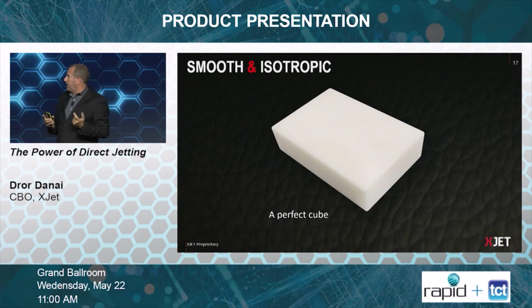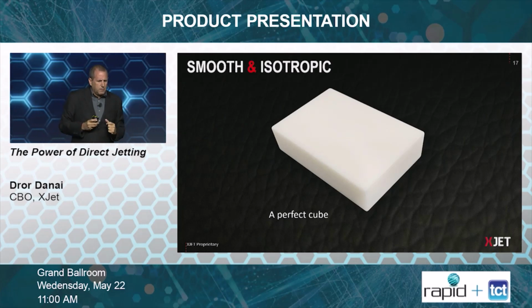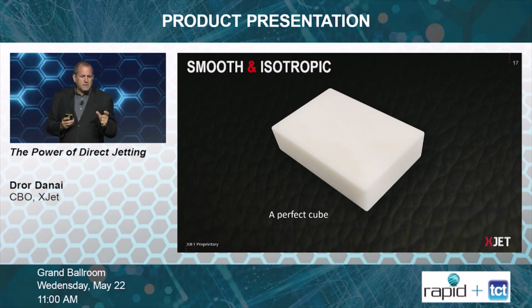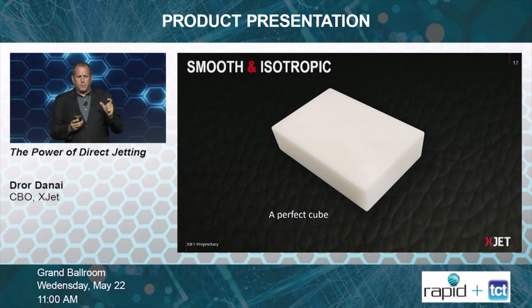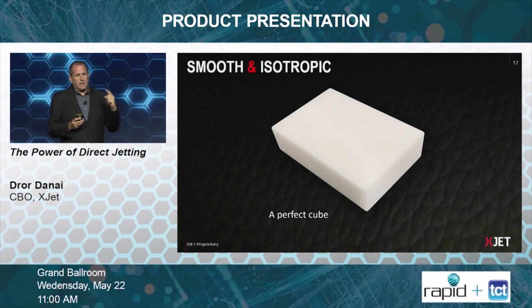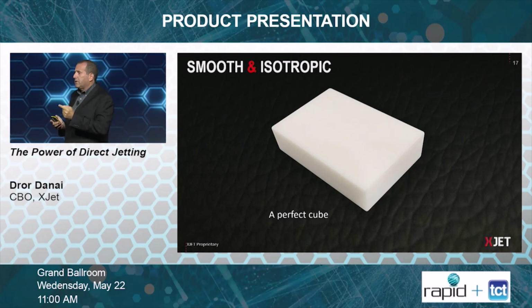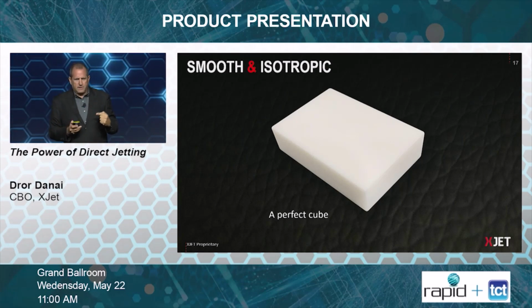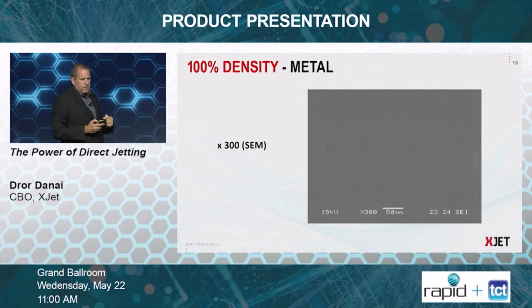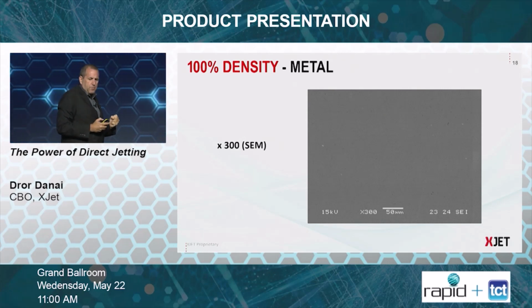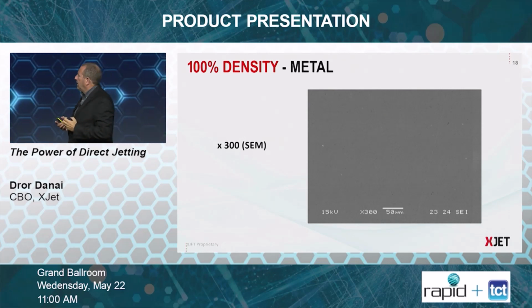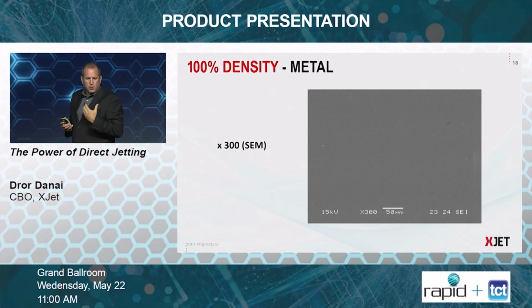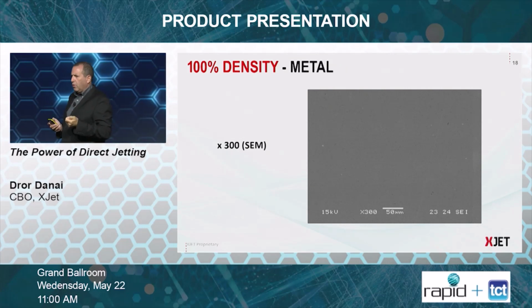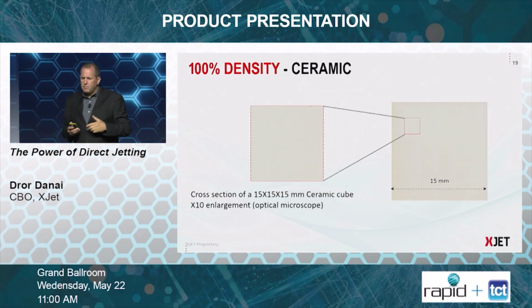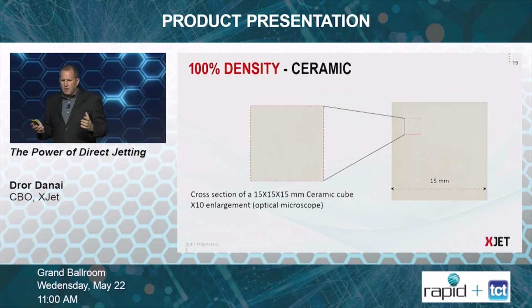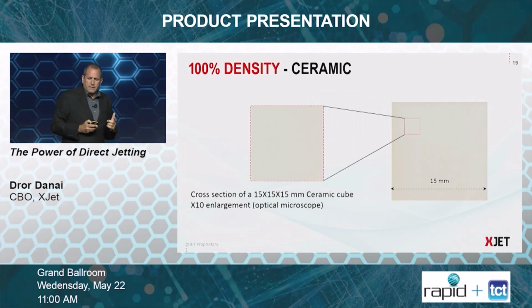The cube that you see, and it's a perfect cube, you may find it on our booth, demonstrates that you could create a very, very smooth surface from all sides and all axes. And this part was not polished or machined at the end. If we look at this microscope cross-section of this metal part, you can see there are no defects and no porosity. The same is achieved, even better, on ceramic.